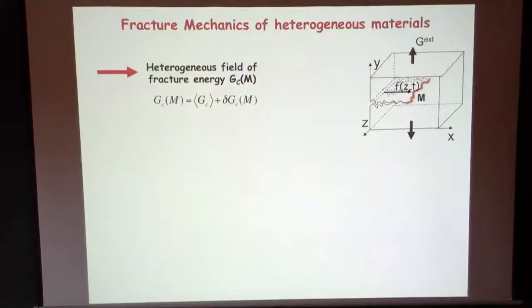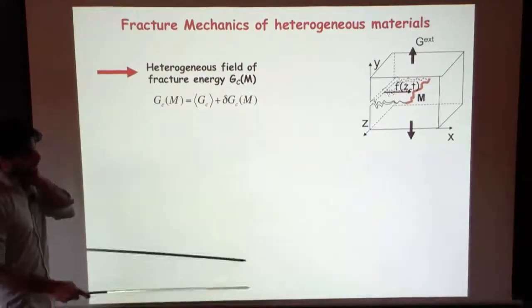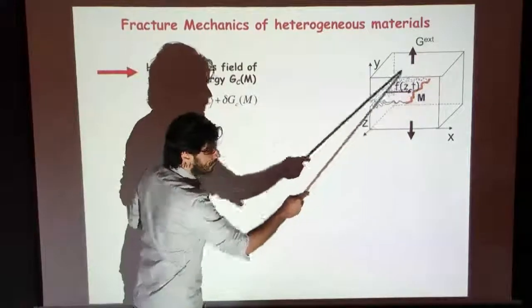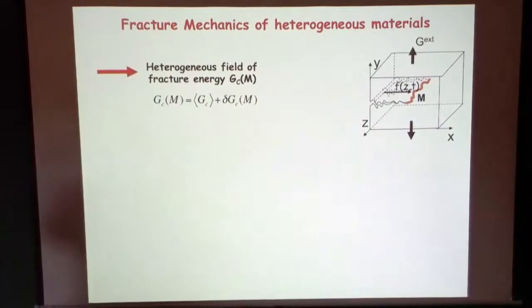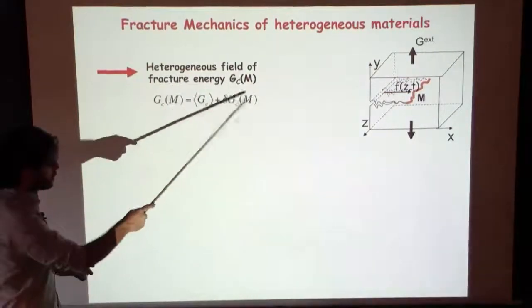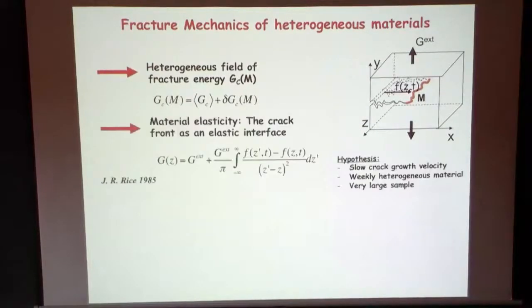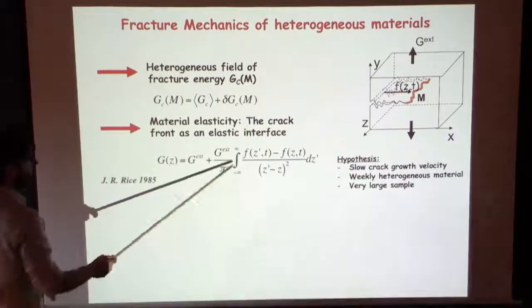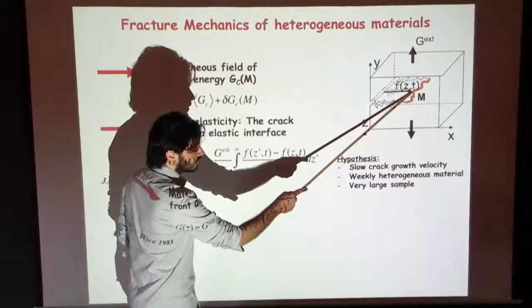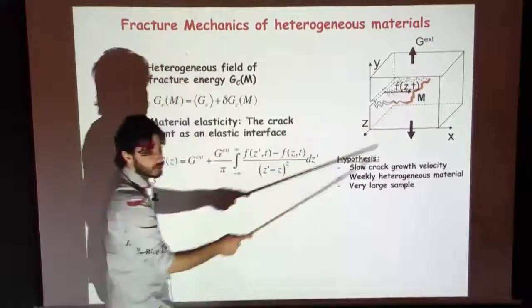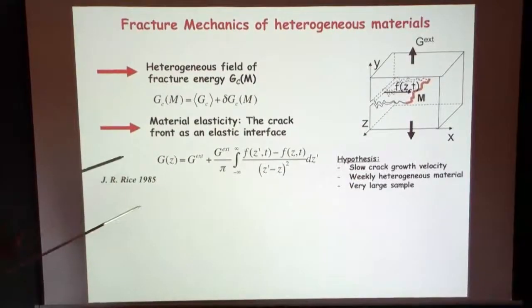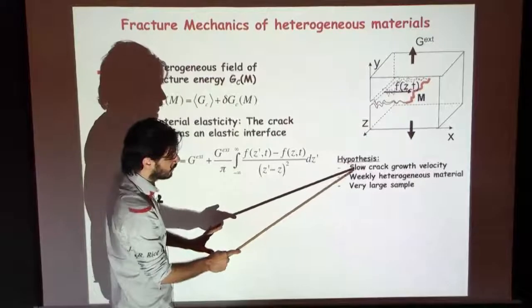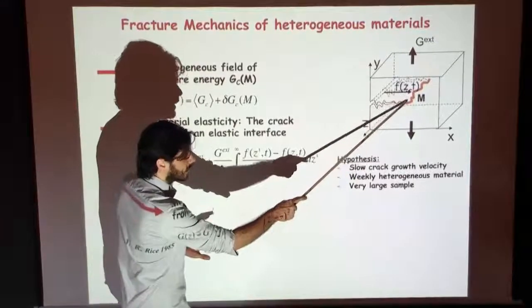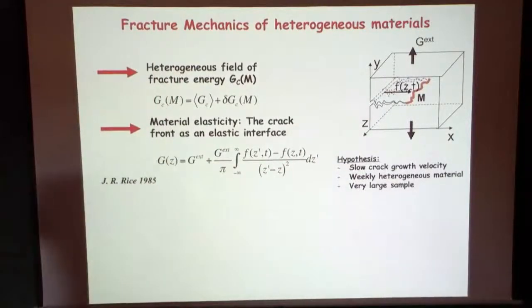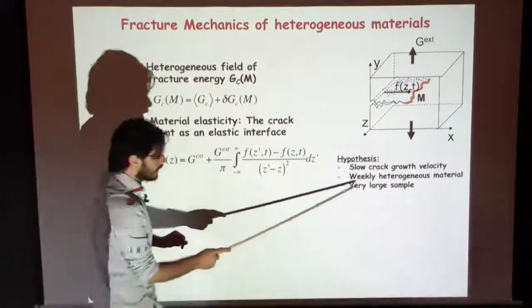So I want to rationalize this effect, and I'm going to introduce now a field of fracture energy, meaning that the resistance may vary with the position you consider in your material. It's going to be written as a constant average fracture energy plus some perturbation that depends on the location you consider in your material, and the key point is going to be what is the value of the local driving force at some point as a function of the geometry. So I'm going to address this problem in a specific case: slow crack propagation, weakly heterogeneous material, this is important. In that case, I have small out-of-plane perturbations that I will be able to neglect at first order, and a very large sample.